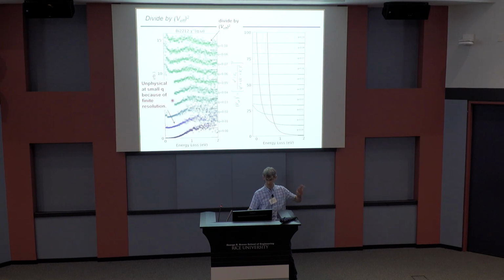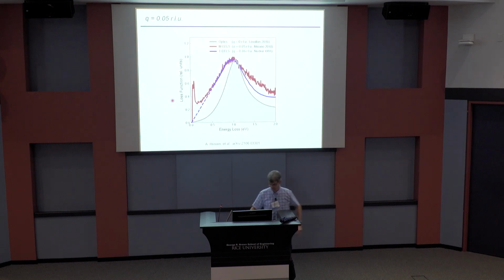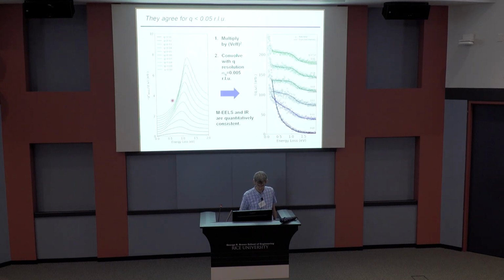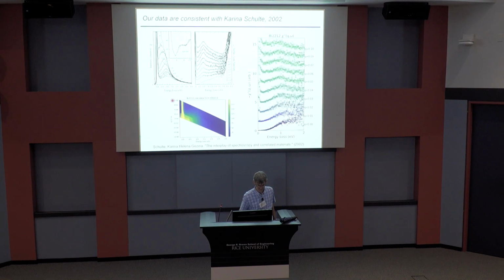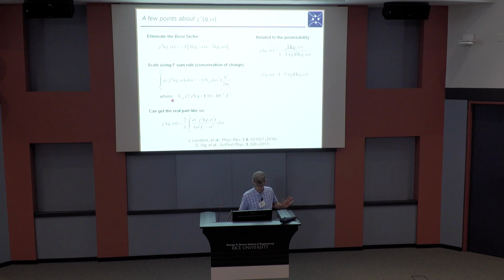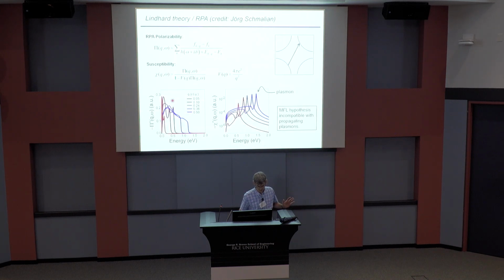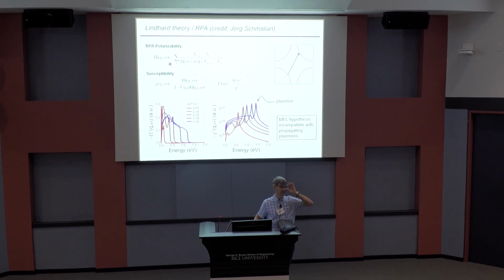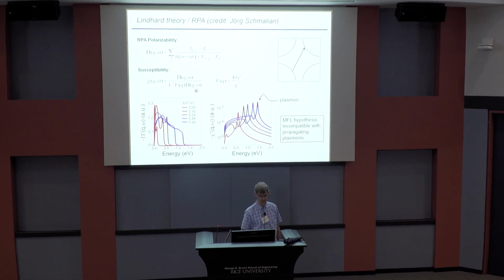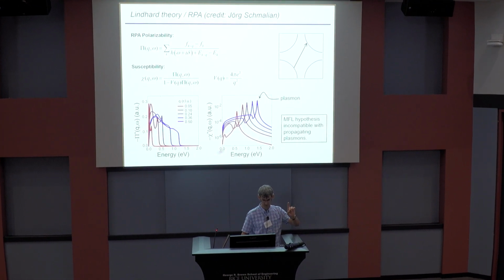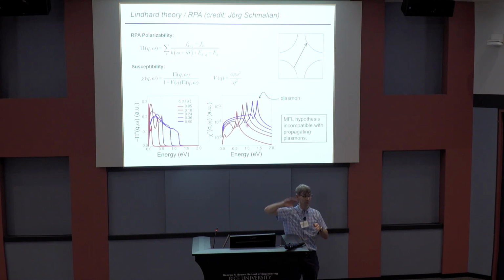All right. You mean, what kind of electron gas? A non-interacting electron gas? I'm glad you asked, because Jörg Schmalian, bless his heart, calculated it for us, just because people ask so much. And here it is. I have answers to all questions. This is what you get. So you're saying, let's pretend I have this Fermi surface, and then I take this out of a different book, Mahan or Fetter and Walecka, and then I compute that Lindhard thing and I plug it in here. What you get is a plasmon with a plasma frequency of an eV that's a dispersing collective mode like you get in aluminum. That's what you'd predict. But you don't see that. That's not seen in the experiment, at least not our experiments. What we get is this marginal Fermi liquid looking thing.